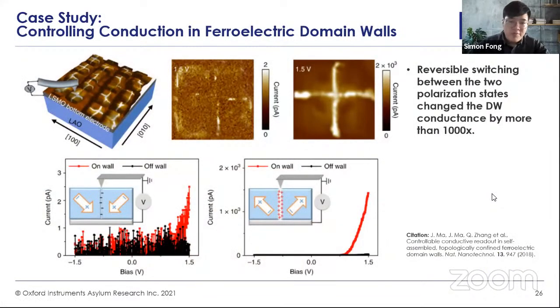Here's another combination of techniques, between PFM and conductive AFM. What the researchers wanted to do is control the conductance of the material through polarization. In a certain polarization state, the charged domain wall closes and inhibits the current passing through, and in the other state, it opens up the domain walls and allows the conductance measured by conductive AFM to increase by 1000%. So this is what the researchers are doing.